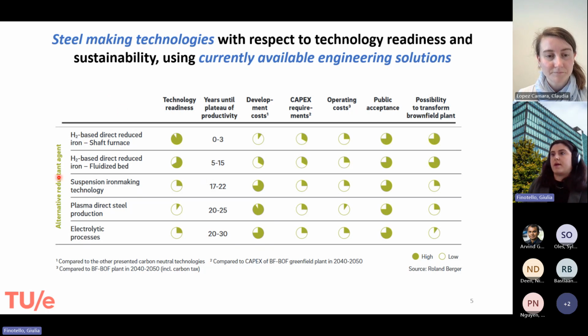This is an overview that puts all these alternatives together. We have a shaft furnace here, and we have the technology readiness level here, together with other properties. What is important to see is that the shaft furnace is already used widely and has a high technology readiness level. Then below we have the fluidized bed reduction. And then you see that we have three other techniques. The suspension iron making technology, which occurs at very high temperature so that the reaction can go very fast, but the technology readiness level is lower. And the same goes for the plasma reduction and for the electrochemical reduction. So we are talking about TRLs which are much lower than a fluidized bed and shaft furnace.